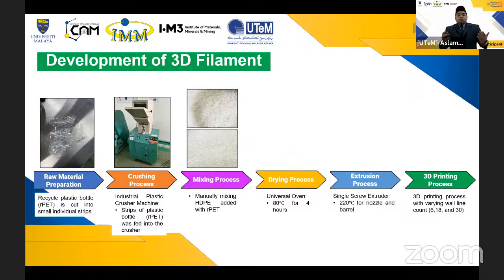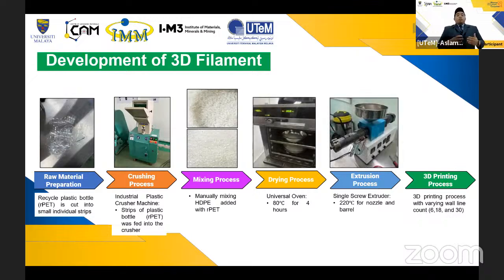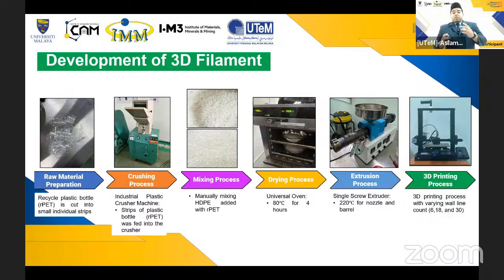So after the crushing process, we manually mix the rPET and the HDPE in a blender at 1% rPET and 99% HDPE. We then proceed to dry the blended rPET in the oven to eliminate any moisture within the material. After the drying process, we proceed to the extrusion process to create the 3D printing filament for FDM. And lastly, the filament itself will be used in the FDM 3D printing process.